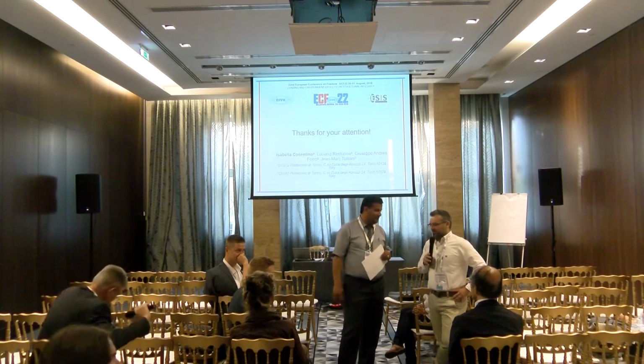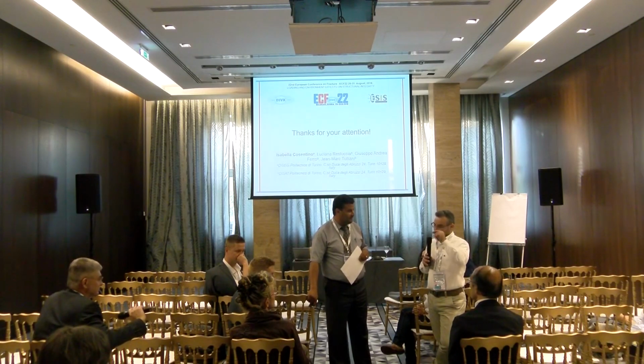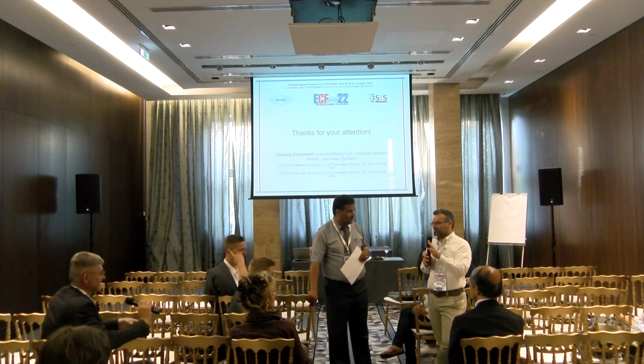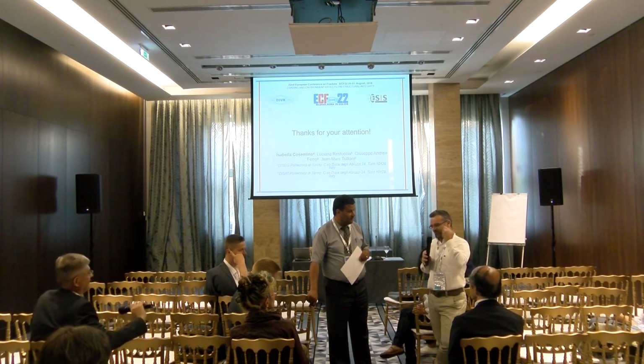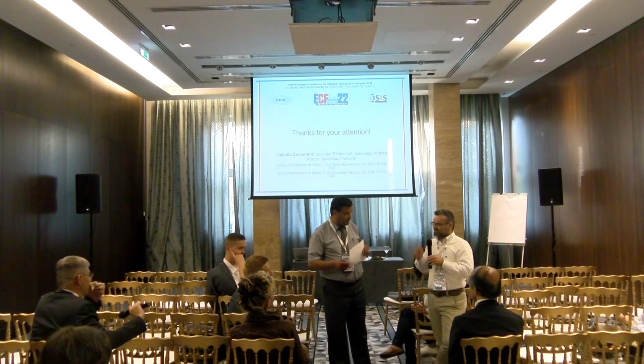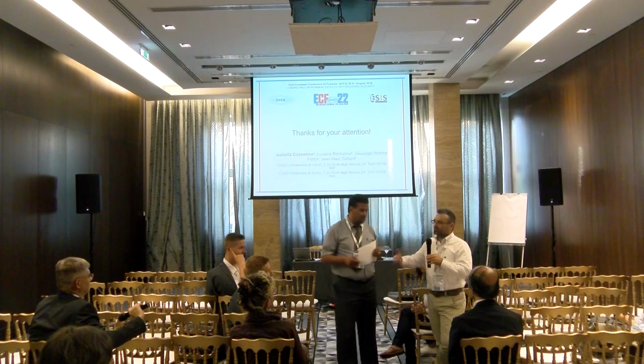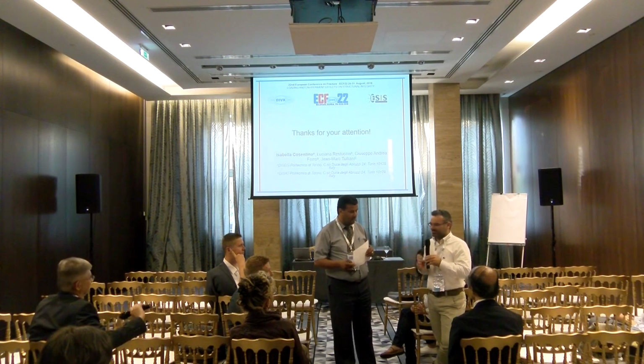Exactly. On Thursday, Eva will show you some pictures showing localized corrosion on the heat-affected zone, while the fusion zone is unattacked by corrosion. We have also performed artificial aging on the weldments, and she performed tensile tests as well. This is a complex phenomenon. We try to give a small solution. We cannot solve everything, of course.